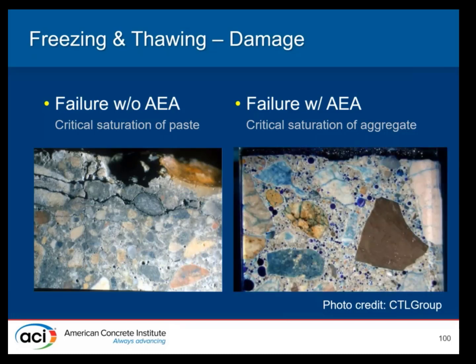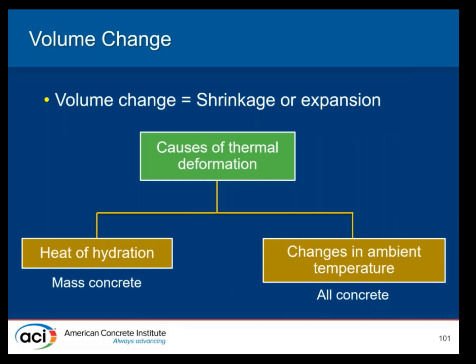And then on the other side, we have air-entrained concrete, and the photomicrograph shows the concrete experiencing freeze thaw. So we get critical saturation of the aggregate. Once the paste had adequate air entraining, but the aggregate itself was porous, and the water got into the aggregate and actually started to expand and cause the damage. Some of the aggregates that may be prone to freeze thaw damage when critically saturated are cherts, clay-bearing limestones, and some of our lightweight aggregates. So freeze thaw damage. The other problem we have is volume change as a result of shrinkage or expansion.